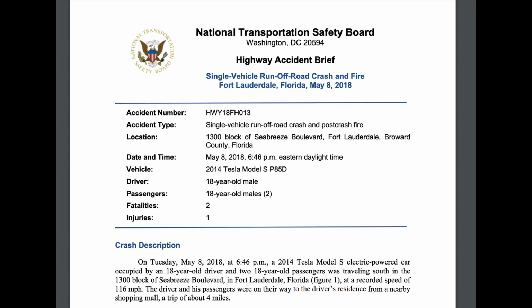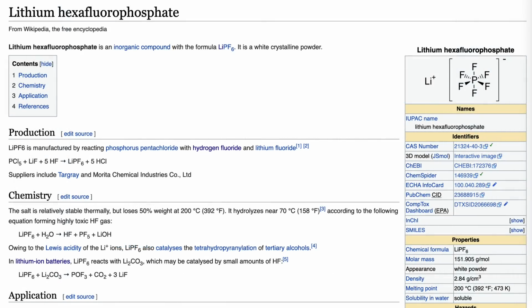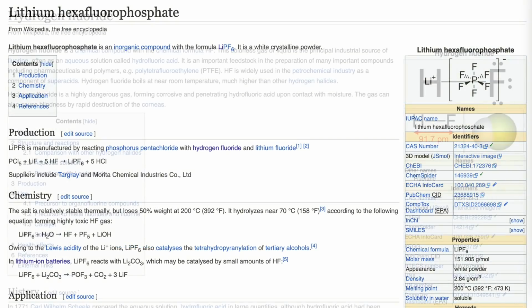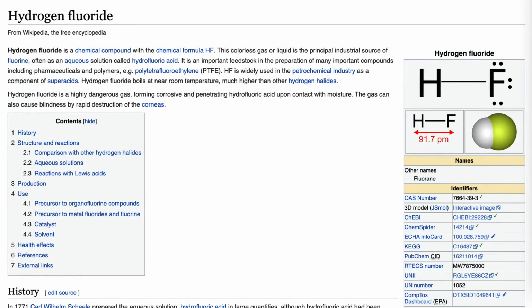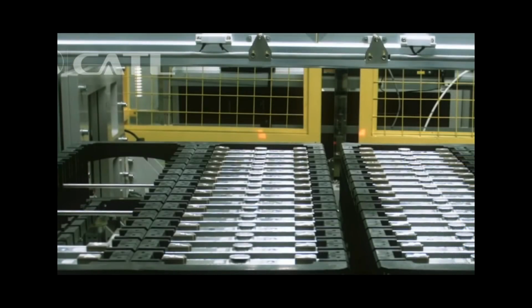Firefighters tend to use water to smother a fire, but this may lead to additional risks. The salt in the electrolyte, aptly named lithium hexafluorophosphate, can react with the water to create hydrogen fluoride, a corrosive gas. Hydrogen fluoride is used in the petrochemical industry to create superacids. Enough said. And water being poured into the battery can cause additional short circuits. It is known that dirty water leaching into the battery's innards can spark EV fires. There have been a few EV bus incidents in China of such.